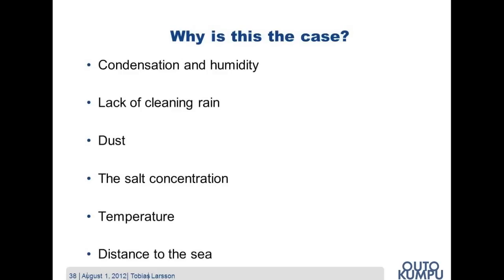Well, I've listed some of the most common reasons, and I won't go into too much detail, but condensation and humidity is one factor, and corrosion can only take place when moisture is present on the surface. You normally talk about this period as the time of wetness, and when you don't have any chlorides present, the time of wetness is defined as the period of time when the temperature is above 0 degrees and the relative humidity is above 80%. When there is accumulation of surface deposits that retain moisture, the time of wetness can be much longer. When chlorides are present, this can begin to occur at 0 degrees and humidity level of 45%.